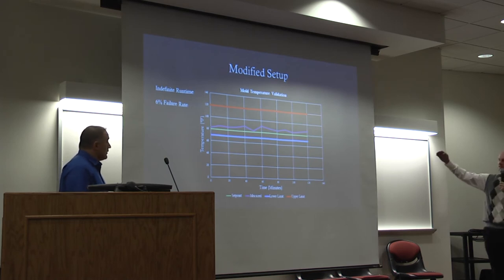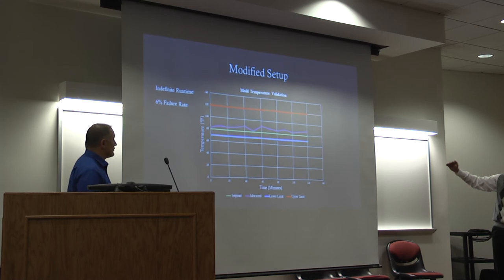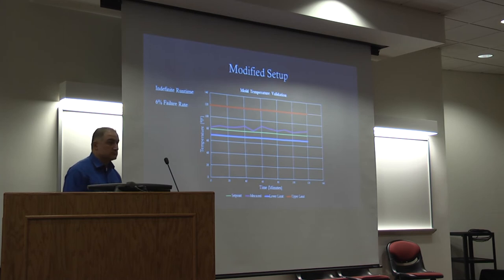This is our modified setup. As you can see, it's got the same upper and lower parameters of 70 to 120 degrees. The green line that you can see is the set point of 80 degrees that we set on the temperature controller, so that's the temperature of the water as it's being input. And to confirm that we were holding the mold stably and that the temperature wasn't rising over time, we also took some data on the temperature through our testing run, and we found less than 10 degrees of variation. So we believe that to be fairly indicative that the machine now has a greatly extended runtime, if not indefinite.